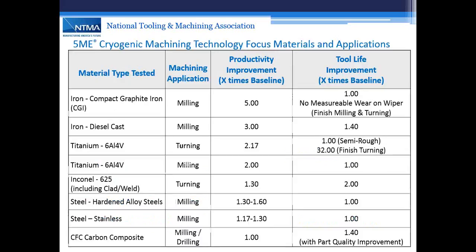Just a quick shot on different materials. I mentioned compacted graphite iron earlier. That particular material, we saw a 5 times speed increase to conventional with equivalent tool life. Diesel irons, we saw 3 times with a 40% tool life increase. So what that tells me is if we were looking for equivalent tool life, that should be maybe 4 times to get rid of that extra 40% of tool life.